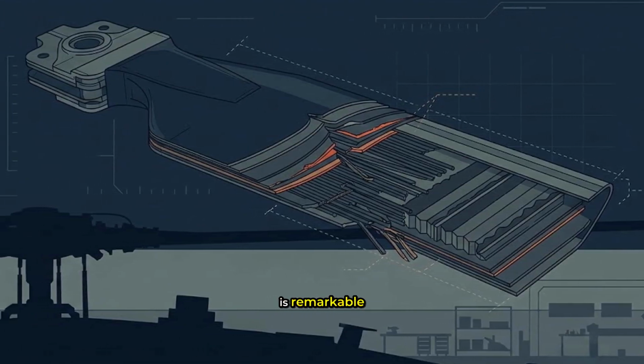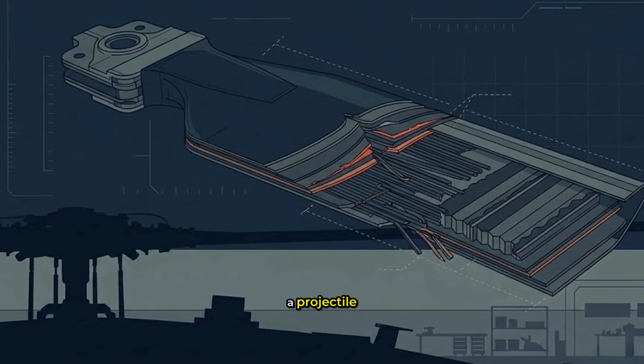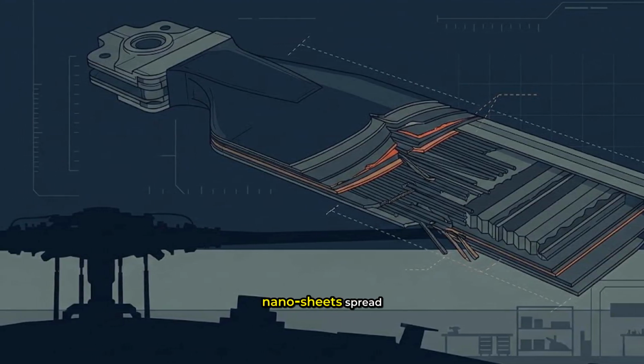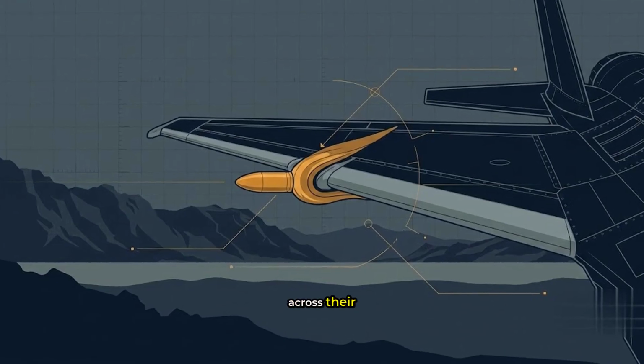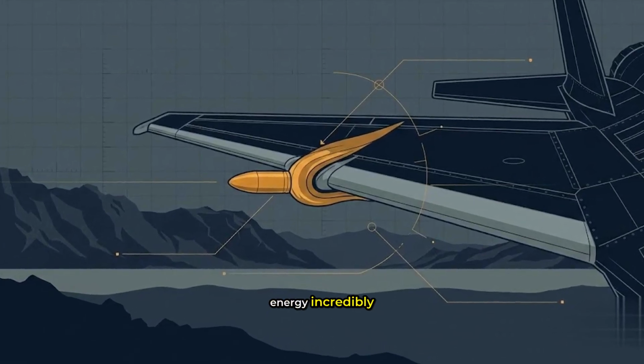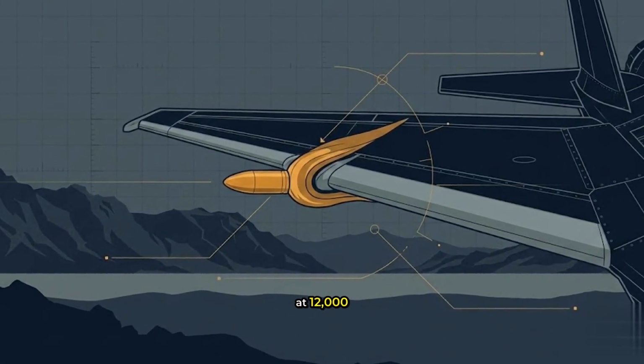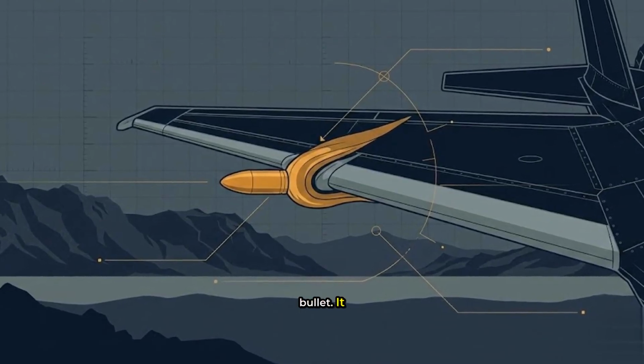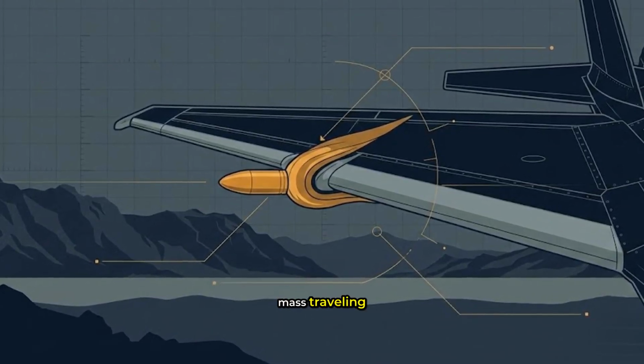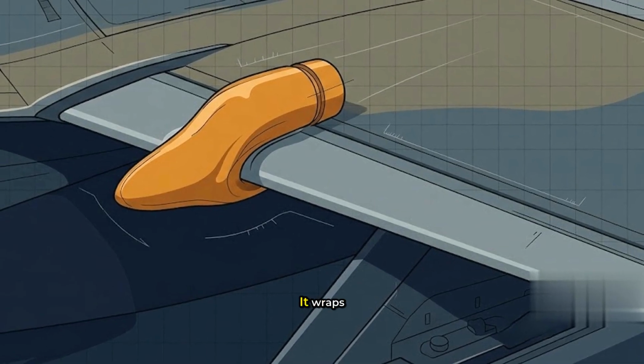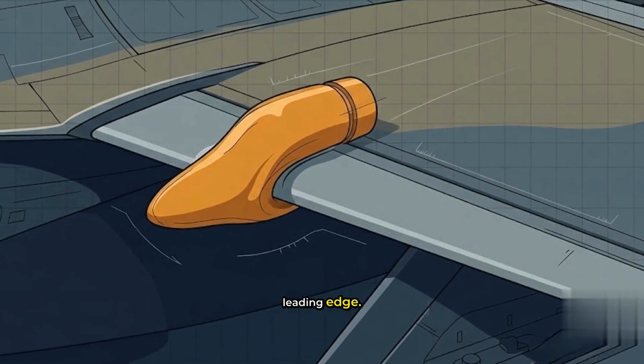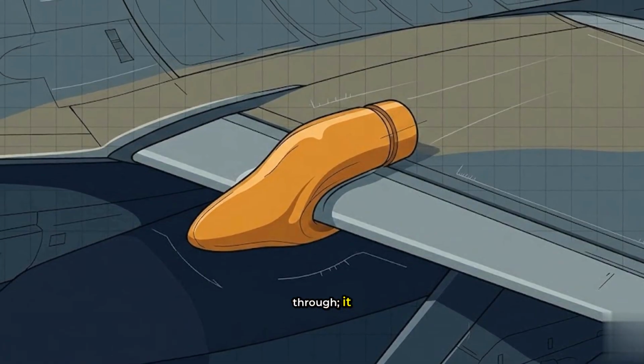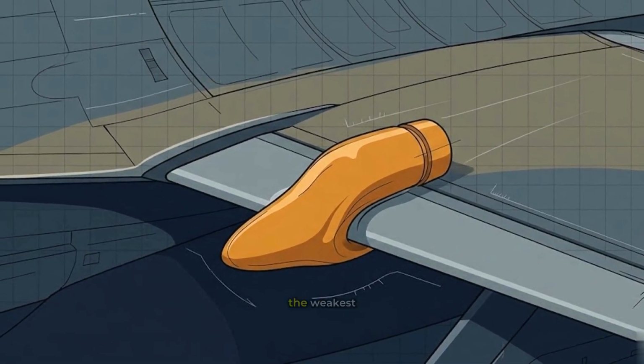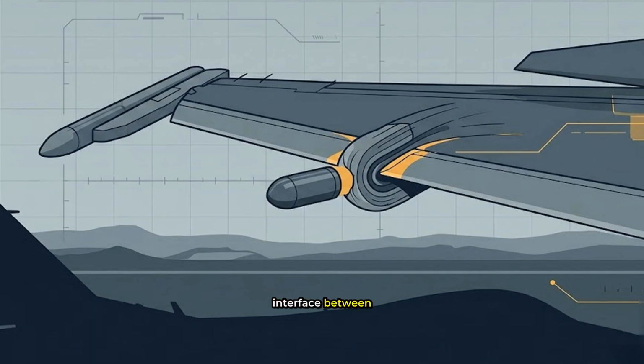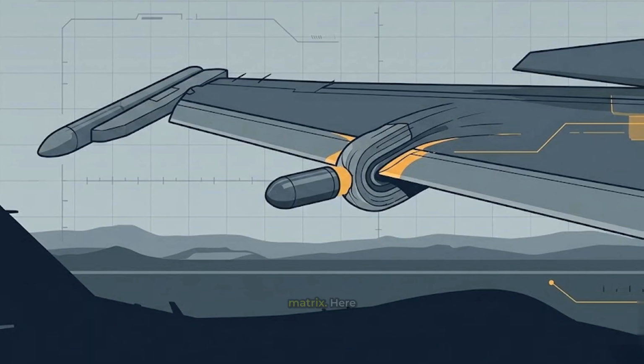Graphene is remarkable at stopping a projectile that hits head-on. The nano sheets spread the force across their plane, dispersing energy incredibly fast. But a bird at 12,000 feet is not a bullet. It is a soft, deformable mass traveling at over 250 knots. It wraps around the leading edge. It does not punch through, it peels. And peeling exploits the weakest link, the interface between graphene and the polymer matrix.